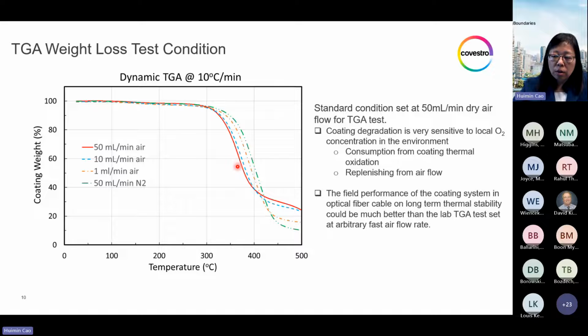And if the flow rate is very slow, such as 1 milliliter per minute, it's actually very close to nitrogen condition. The indication of this is that the coating degradation behavior is very sensitive to the local oxygen concentration sitting on top of the coating. So when the oxygen is consumed from the coating thermal oxidation reaction, it needs to be replenished from fresh air to maintain the reaction rate.